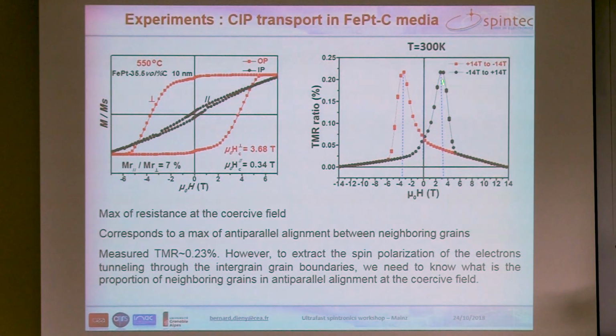So you see here the magnetoresistance response of the media with this in-plane current, and it looks like a GMR, a current-in-plane GMR or current-in-plane TMR, with maximum of resistance close to the coercive field. And this can be understood by the fact that at the coercive field, this is when you have maximum number of grains which are in antiparallel alignment. And on the contrary, at saturation, all grains are parallel. So this increase of resistance is really due to the change from parallel to antiparallel orientation of the grains.